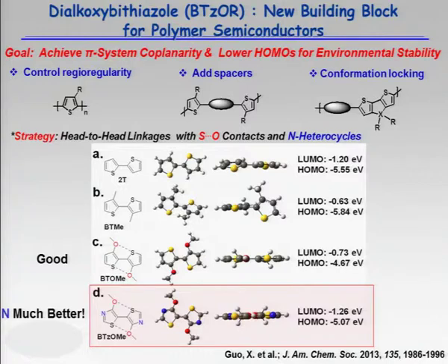But when I add these methoxy groups, look how the HOMO goes right back up in energy. And you can't live with that because it's too electron donating. So we add nitrogens in the ring. And nitrogen has the effect, you can see, compare these numbers to those, to those, to those, of dropping the energies of the HOMOs and LUMOs.